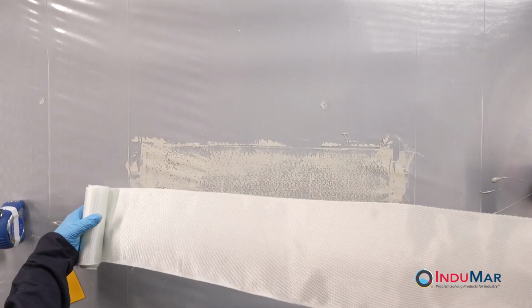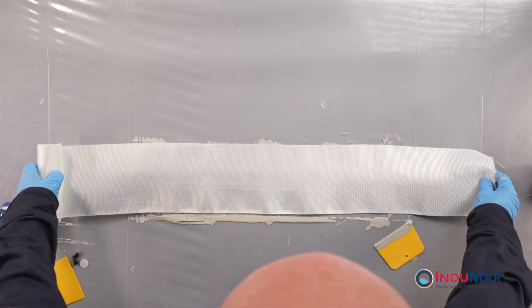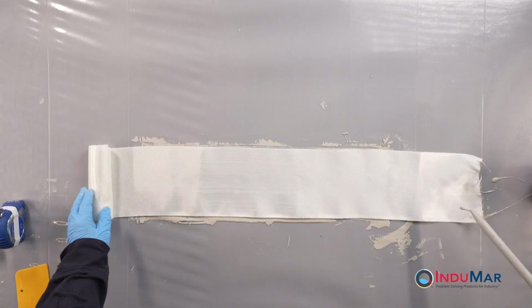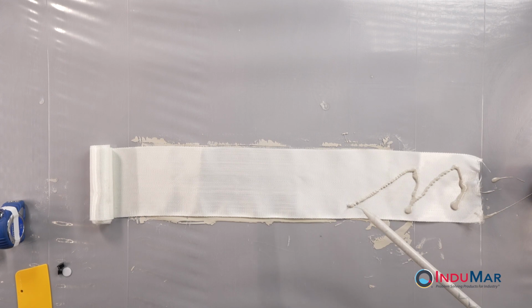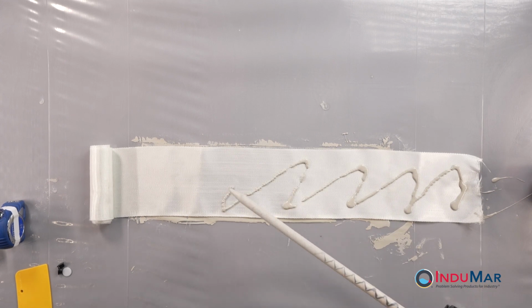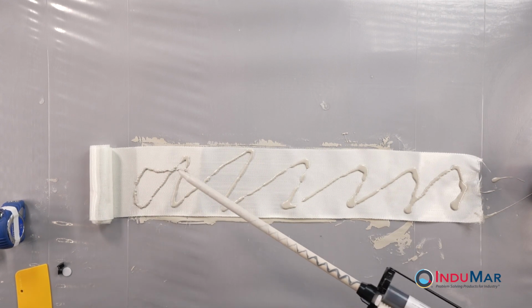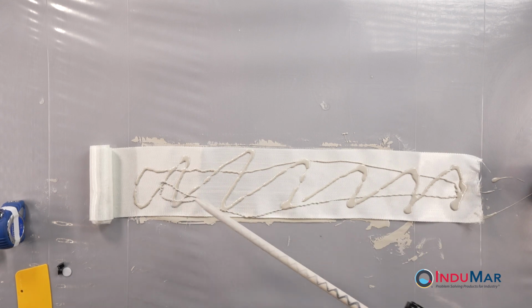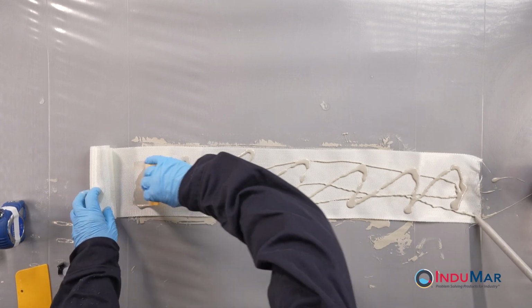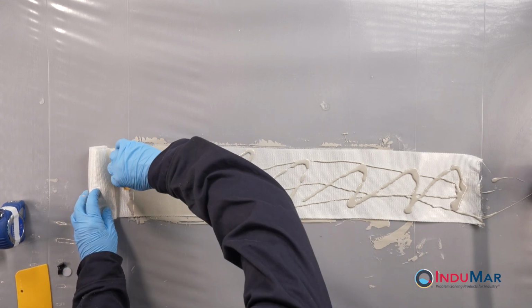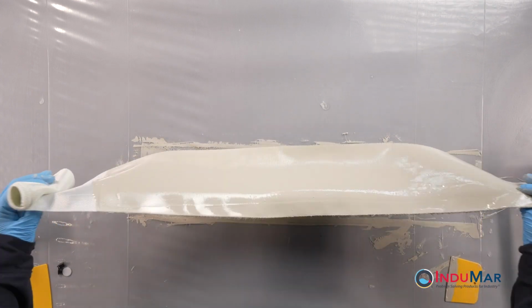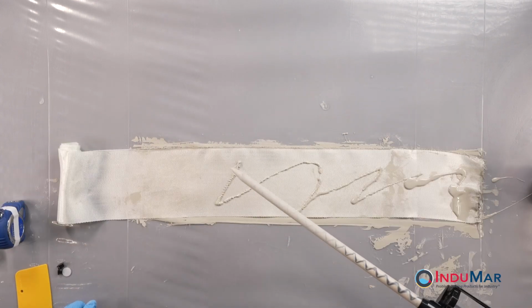Next, prepare enough of the fiberglass reinforcement to accomplish 3 circumferential wraps, again consulting the provided instructions for the quantity of resin to be used for each side of the fiberglass. Evenly dispense the required resin across the surface. Work the resin to the edges, but avoid pushing excess resin onto the plastic. When no dry spots remain, flip the fiberglass and repeat the process.